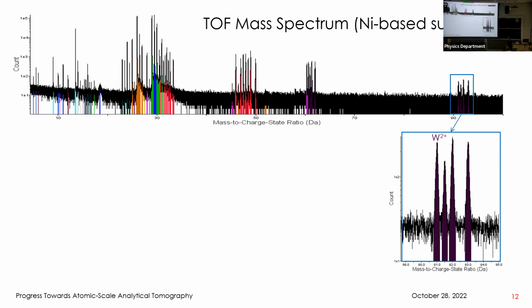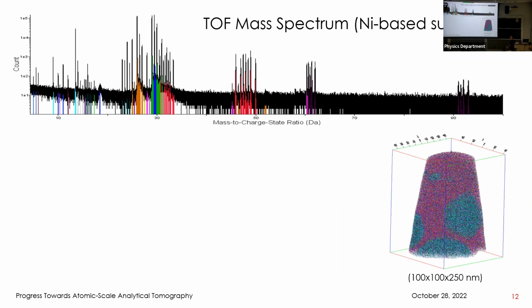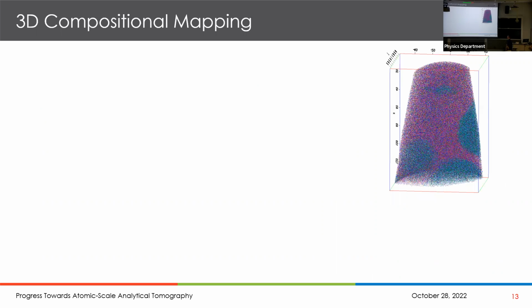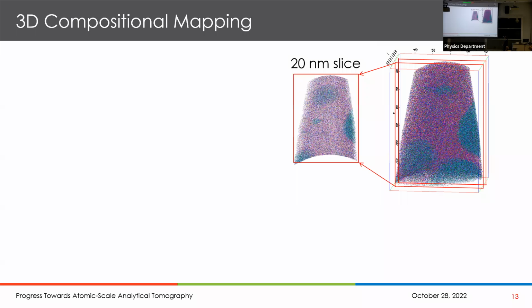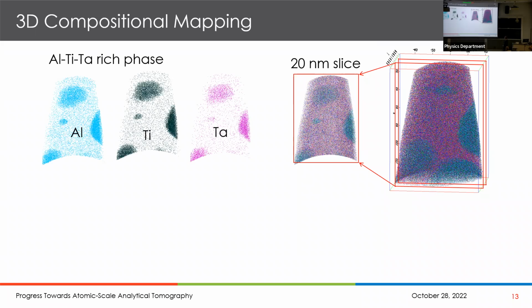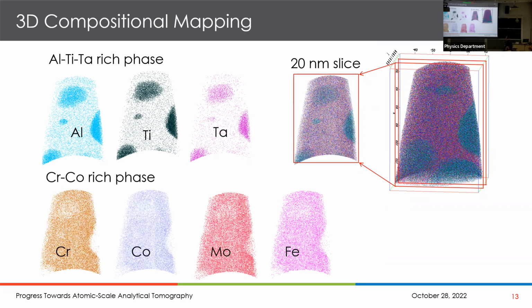All right, so once you are confident that you know what all these peaks represent, you can say, I'm going to identify the atoms in this peak as tungsten and so on. And you can then reconstruct not just where the atoms were, but what their identities are. And so here's a smaller part of an image where you can see the different atoms displayed by colors. And if we think about making slices in that, let's say we take a 20 nanometer slice from that 3-dimensional image, and you can say, well, let me just show me these elements, aluminum, titanium, and tantalum. Those are the ones that tend to go to the intermetallic phases. Or you could look at some of the other elements that tend to reside in, in this case, a substitutional BCC phase. And so there's some powerful three-dimensional compositional imaging.